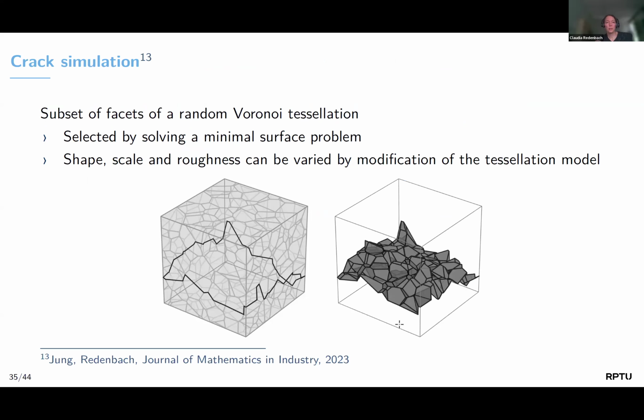How did we do that? How did we simulate the cracks? It's also based on a Voronoi tessellation. What we did here is we selected a subset of the facet system by solving a minimal surface problem in the tessellation. Starting from such an initial curve, we found a closed surface, which is then our crack shape.